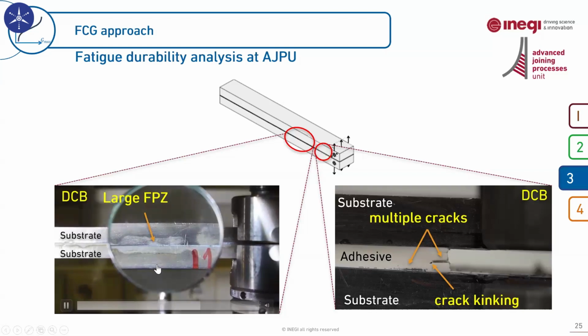The energy here is spent partially in developing this large process zone ahead of the crack tip, and also for opening the crack itself. But we need to be careful here because the crack opens within an already damaged area. And so the energy that we finally measure out of this test is the energy of the system, both whitening and damage zone plus the opening. And then using this energy that we measure cycle by cycle, we can construct and plot the Paris law curve.